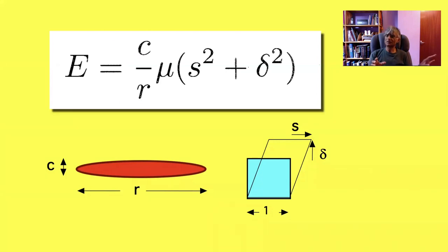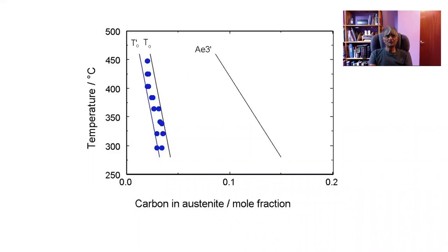Now, of course, when doing the T0 calculation, we have to take account of strain energy because that's a large component of a displacive transformation. And because the bainite plates are fine, they have a small aspect ratio of about 0.02. So the energy due to the displacive transformation is of the order of 400 joules per mole, the strain energy caused by this shape deformation. But the values of the shear and dilatation are very similar to those of martensite. So to take account of strain energy, I'm going to use the T0 dashed curve, which accounts for strain energy as well. And that would raise the ferrite free energy curve relative to that of the austenite. And when we do experiments, you can see that the reaction stops basically when diffusionless transformation becomes impossible.